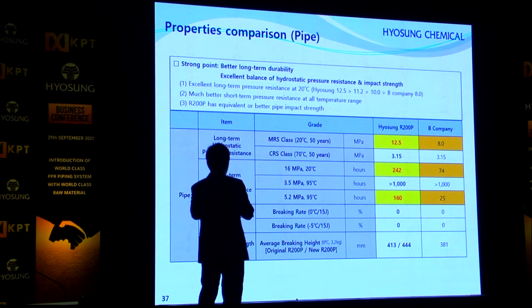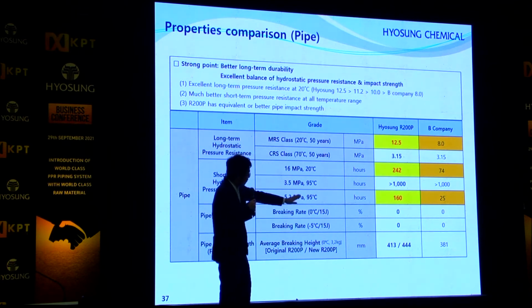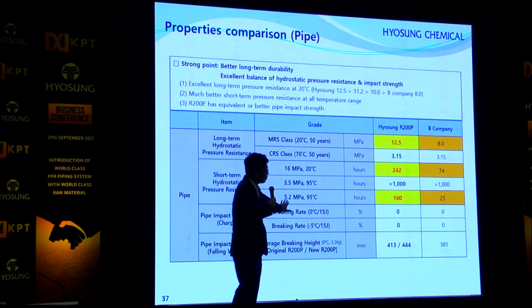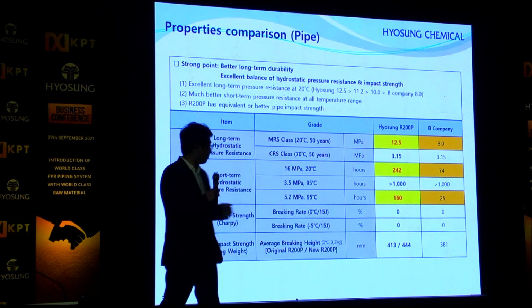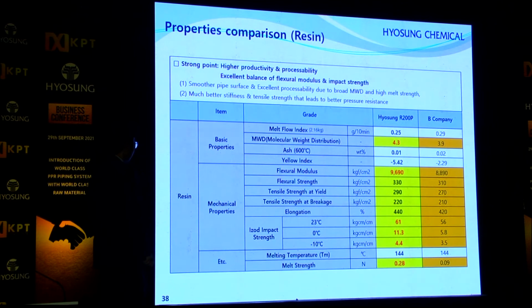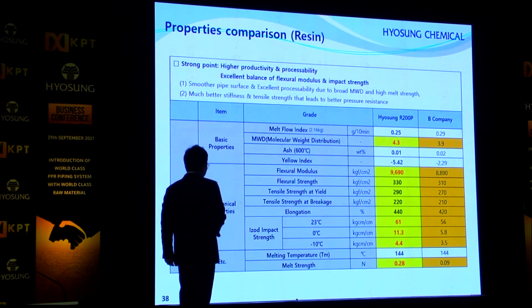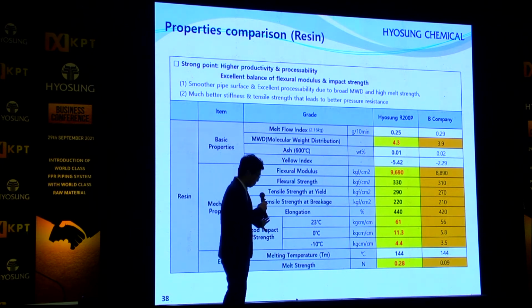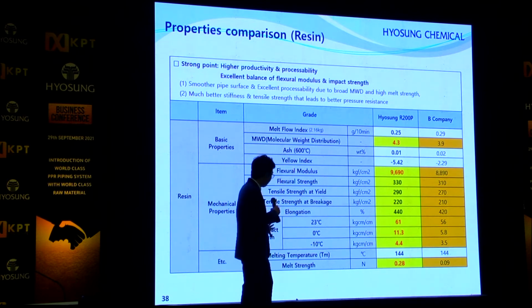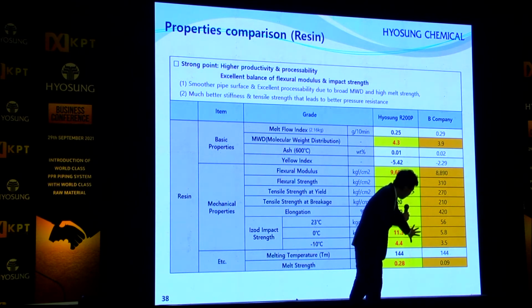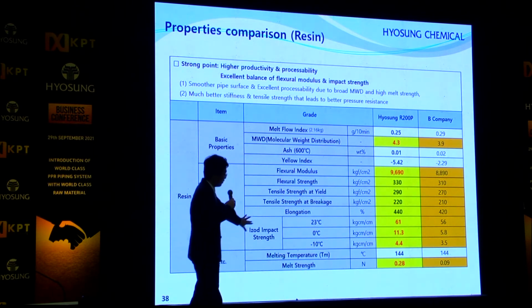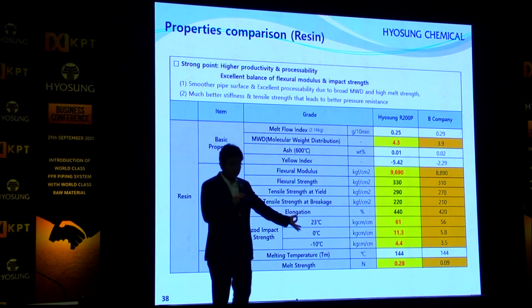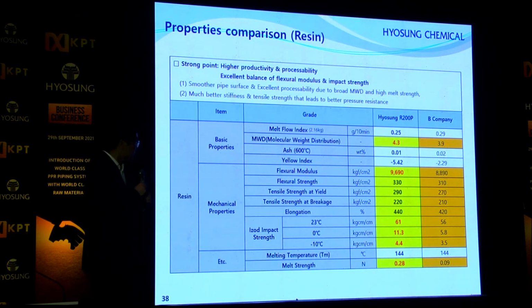And at higher temperature, it's 25 hours versus 160 hours, so we have more than 4, 5, 6 times the durability. These impact strengths I already told about, but if we compare with the same PPR material from the big company, at room temperature it is similar, 61 and 56, but at 0 degrees C, it is 11.3 versus 5.8. So we can say that pipes with R200P have a wider operating temperature range because they stand better at lower temperatures too.